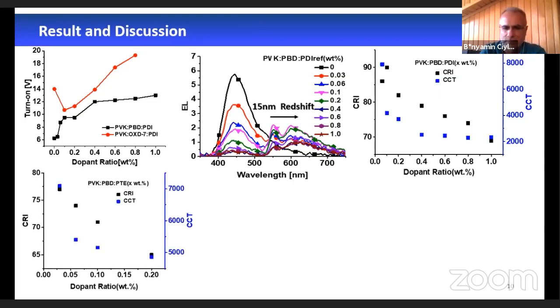The amount of PTE needed for reaching the best white light properties was much less than the PDI-based device. This indicates a high energy transfer between host and PTE compared to PDI. Just like the case with the PDI-based device, CCT and CRI values decreased when PTE weight percent was increased.